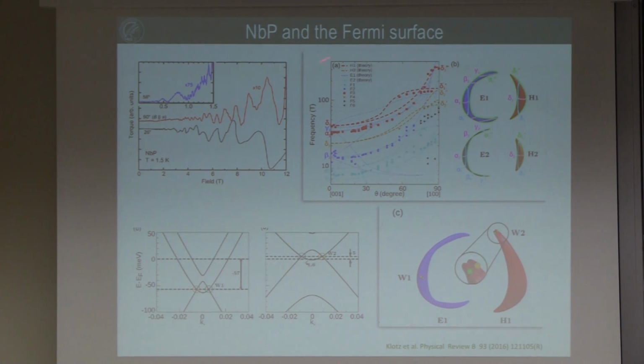This was done with Elena Hassinger's group; you can really nicely assign all the oscillations. So this is a calculated band structure, the electron and hole pockets, and then you see these features, these lines here, are the assigned frequencies seen in the quantum oscillation.